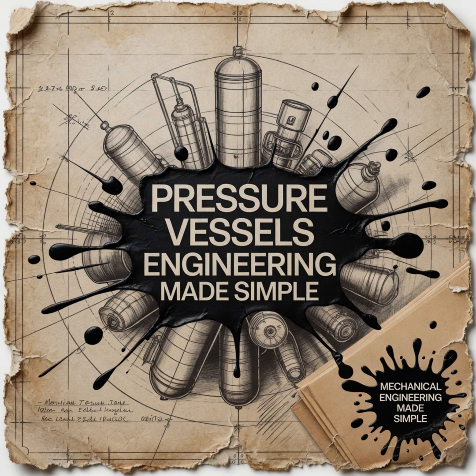But RT is incredibly poor at finding tight, planar defects, like severe cracks. A crack is a structural failure, but it doesn't take up any volume. The two faces of the broken steel are pressed tightly against each other.